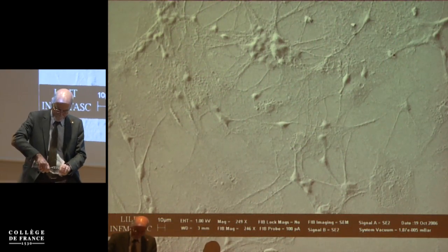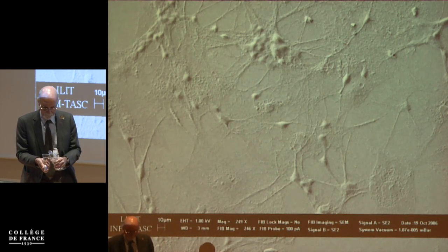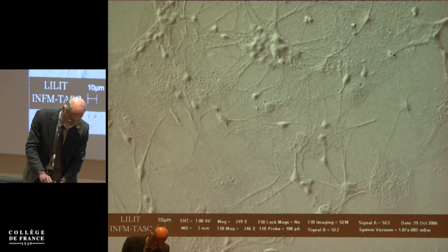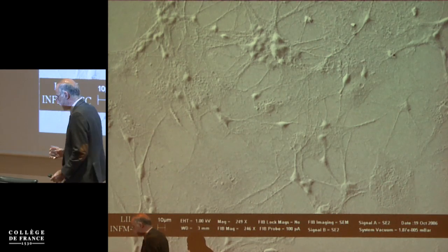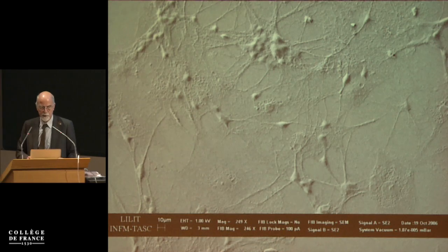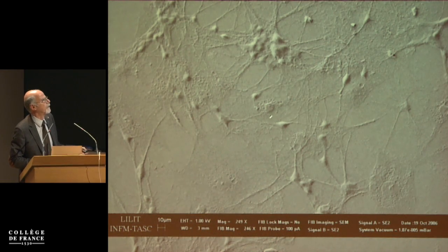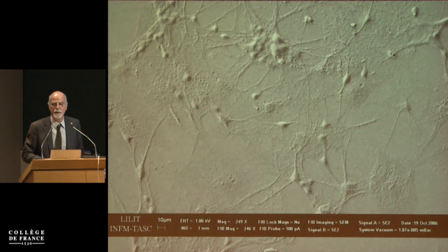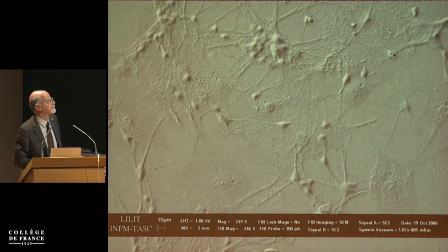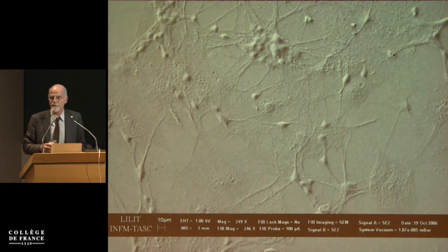When we grow the neurons, they grow very well. So it looks like neurons have a very high affinity for carbon nanotubes. The morphology is exactly the same. It's the natural morphology. So they are completely identical to the reference neurons. The dendrites elongate very similarly.